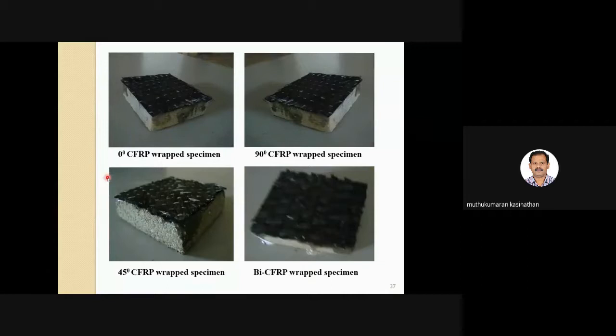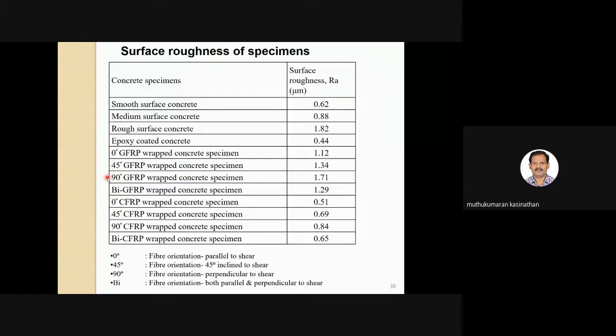We have used both glass as well as carbon. And we measured the surface roughness using a roughness measuring device. The smooth concrete surface has a roughness of almost 0.62. Typically one is the ideal case roughness, a very high roughness. Accordingly, the smooth surface has only 60% compared to the ideal one. The medium surface is almost 88%. For the rough surface, the roughness is beyond the expected one, close to 1.82. We purposefully introduced a very high roughness. In fact, we witnessed that we could get this much roughness when going with the bored cast in situ pile.